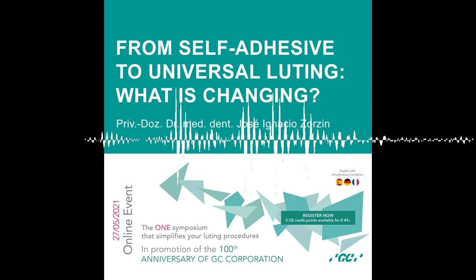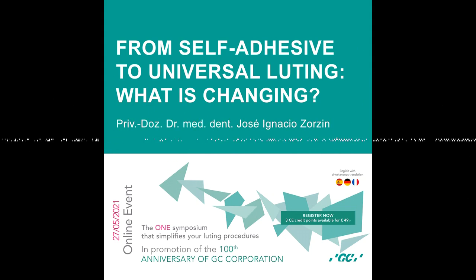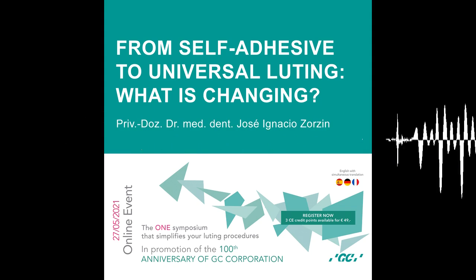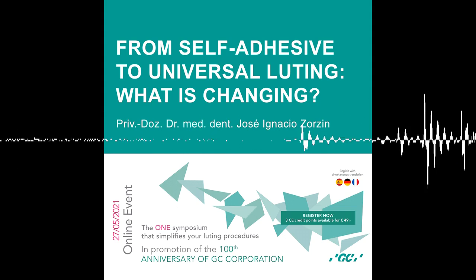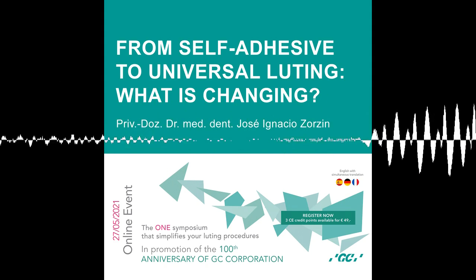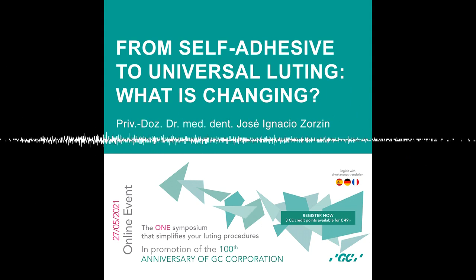And maybe for all the materials where we have good retention and you also want to have adhesion, there you can use self-adhesive resin cements. But always there where you need a maximum of adhesion and you go for very thin restorations, then you should always think about maybe going for the conventional adhesive pathways. And now let's see how this changes with these new universal self-adhesive resin cements.